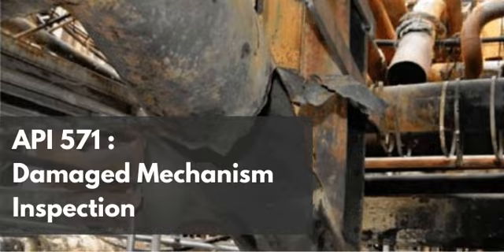Exactly. The invading carbon chemically binds with elements like iron and, very specifically, chromium to form complex molecules called metal carbides. And these metal carbides are entirely different beasts from the original metal. They are incredibly hard, and critically, they are severely brittle. They're essentially microscopic, ceramic-like structures forming inside the metal matrix.